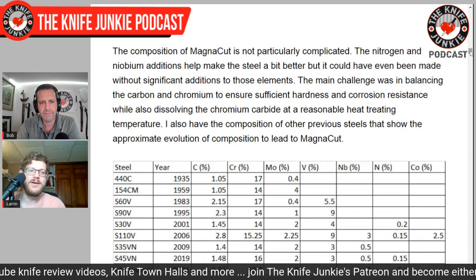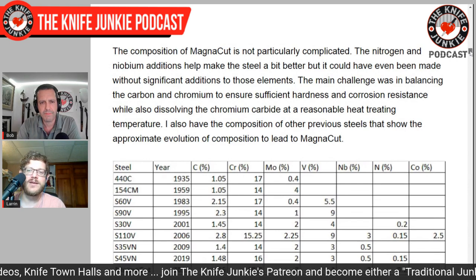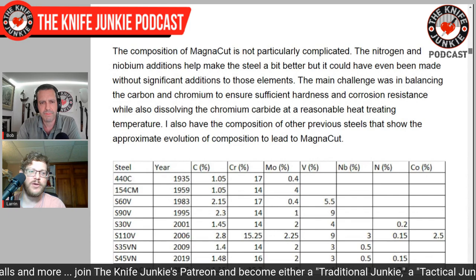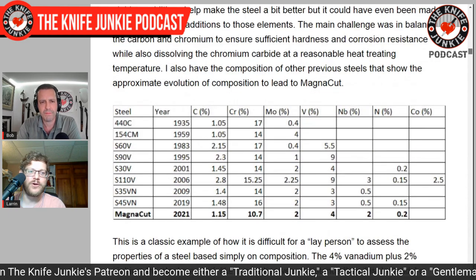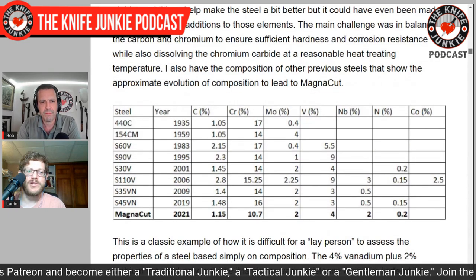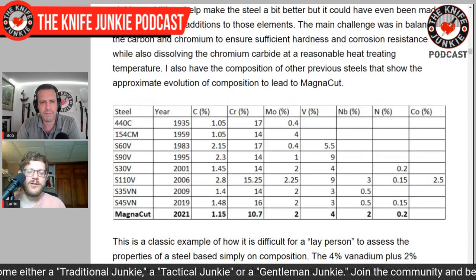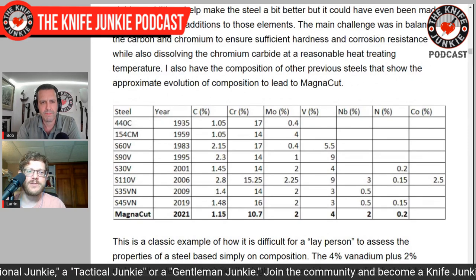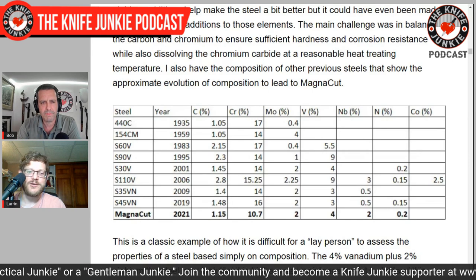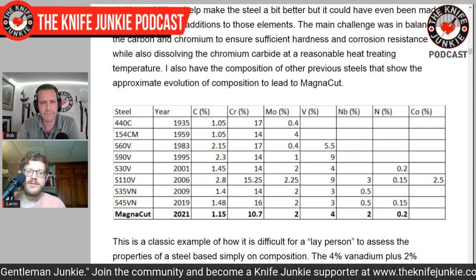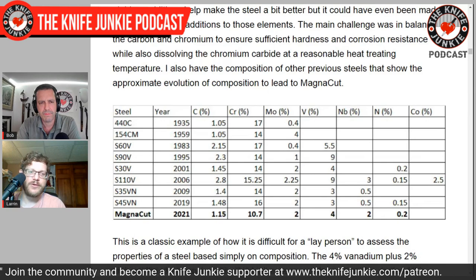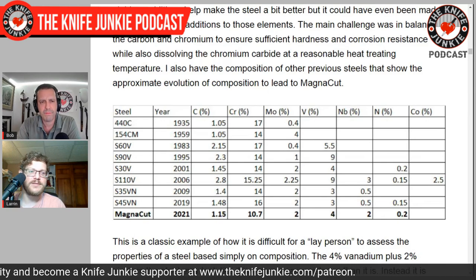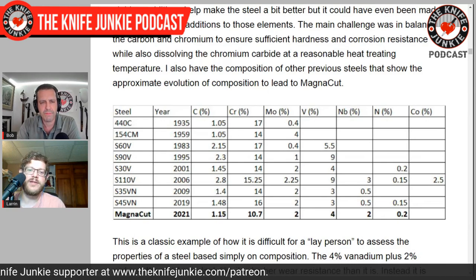And when I say the best non-stainless grades, I don't mean 1095. I mean like CPM-CruWear, CPM-4V, Vanadis-4 Extra. Those are powder metallurgy non-stainless steels with really high combinations of toughness and wear resistance. A better combination of those properties than is available in stainless steels. That includes M390, S30V, LMAX, much better than those steels, but they are not stainless. And really, when we're talking cutlery steels, knife steels, we want corrosion resistance. We would prefer to have it.